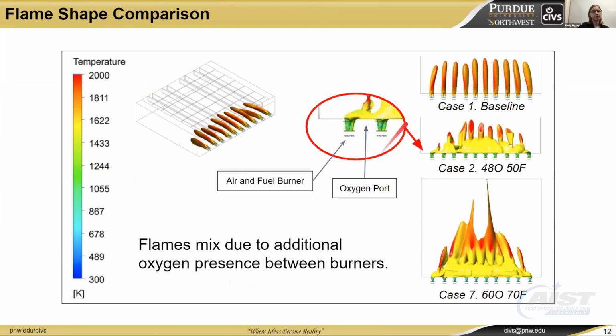So here we can see a top view comparison between the flame shapes for the baseline case, case 2, which was the optimal low enrichment case, and case 7, which is the optimal medium enrichment case. The zoomed in view here shows where oxygen ports were located relative to the burners. And one of the main things that we can immediately note from this is the lower temperature flame bank occurring all along the burner wall. So this occurs due to the fact that oxygen is not only injected at the burners for these cases, but it is also injected in between them at the ports, so the flames are able to mix.